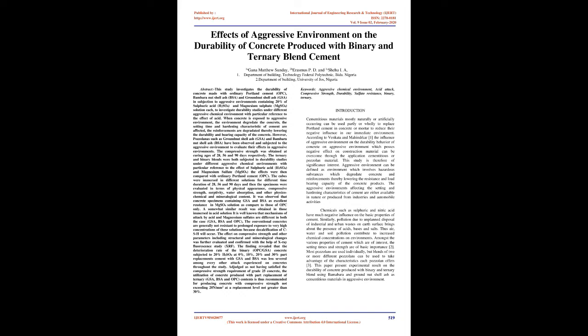The findings revealed that the deterioration rate of the binary OPC/GSA concrete subjected to 20% H2SO4 at 0%, 10%, 20%, and 30% partial replacement of cement with GSA and BSA was less severe among every other attack experienced on concretes throughout the study, adjudged as not having satisfied the compressive strength requirement of grade 25 concrete.